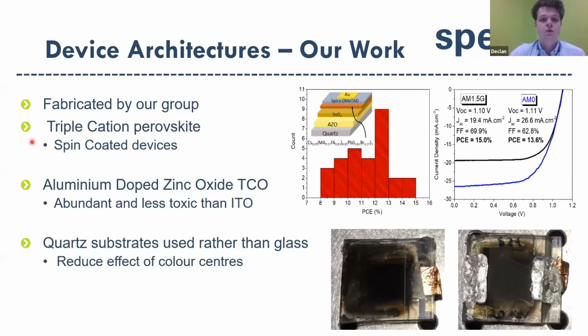For this work, we fabricated our own spin-coated triple cation devices. We replaced the more common ITO with AZO, making it more abundant and less toxic, no longer using the element indium. We use quartz substrates, which reduce the effect of color centers, which are darkening of glass due to radiation interaction with the lattice structure. We also tested devices at AM1.5G and AM0, AM0 obviously being more relevant for space applications.